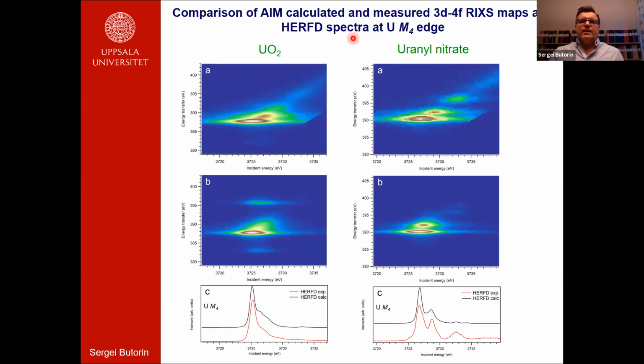This slide shows a comparison of Anderson impurity model calculations results, like RIXS maps and HERFD spectra, for two compounds, uranium dioxide and uranyl nitrate. For uranium dioxide, of course, the charge transfer effects and the hybridization effects are not that strong here. It was just used as an example, as a model system. So the HERFD spectrum is not very different from the calculations using only the crystal field multiplet, because the charge transfer energy in this system is quite large.